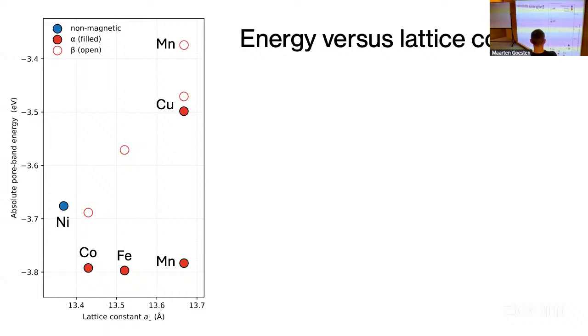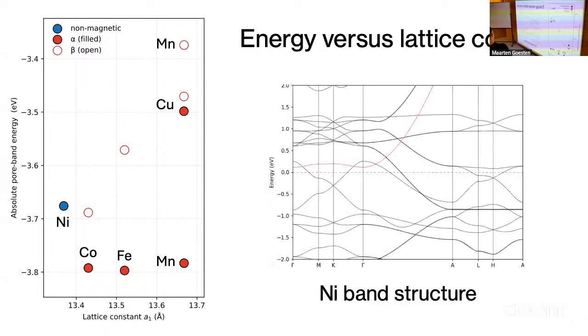But we see that there appears to be some optimum. We can go as much as almost 4 eV below the vacuum level, which is really considerably lower than anything that people have seen before with these systems.